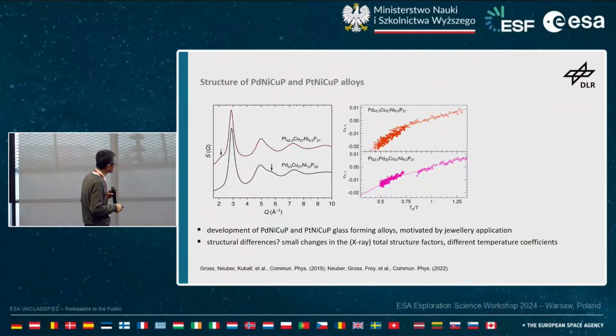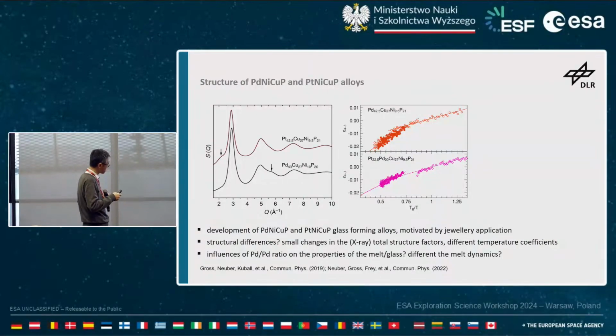In this case, there is a development of palladium and platinum alloys, and what they found from a structural point of view is that there are subtle changes if one gradually substitutes platinum with palladium, and also with temperature. If you look at the temperature dependence of the first shell, there are differences as a function of temperature, so expansion, if you want. We are really interested in the ratio between palladium and platinum, and other properties like heat capacity and crystallization behavior also change with this ratio.